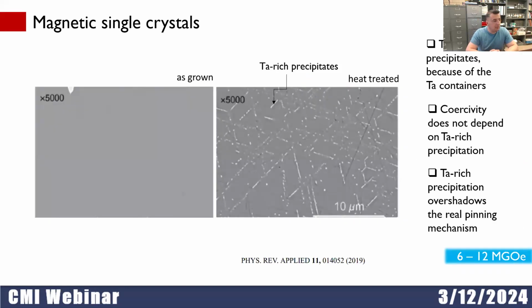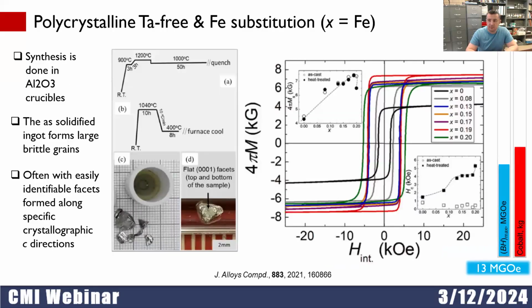So we were wondering what is the structure of single crystals, and at the beginning, when we did our synthesis in the tantalum crucibles, we found precipitates after the heat treatment. But those precipitates were tantalum rich, but they were not related to the coercivity. They were basically camouflaging the real structural defects. So then we avoided tantalum. We did it in very practical alumina crucibles on a small scale, and we added iron to further decrease cobalt concentration, for example, in the original Cerium Cobalt 5 system.